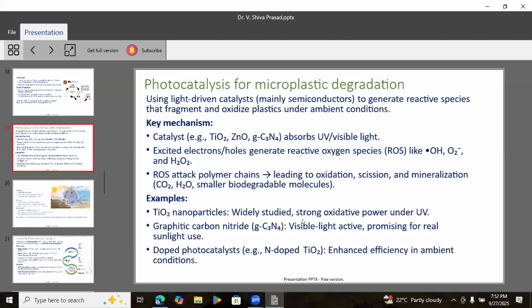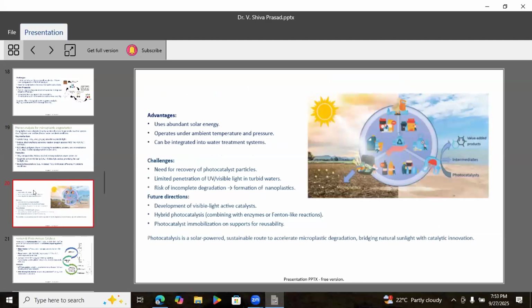For example, titanium dioxide nanoparticles are widely studied for their strong oxidative power under ultraviolet. Graphitic carbon nitride is visible light active, promising for real sunlight use. The advantage of photocatalysts is that they use abundant solar energy. So it operates under ambient temperature and pressure and can be integrated into water treatment systems. The challenges are the need for recovery of photocatalyst particles, limited penetration of UV, and the risk of incomplete degradation. Future directions are development of visible light active catalysts, hybrid photocatalysis combining with enzymes or Fenton-like reactions, and photocatalyst immobilization on supports for reusability.